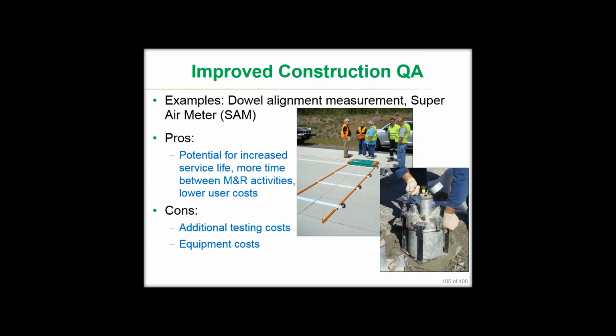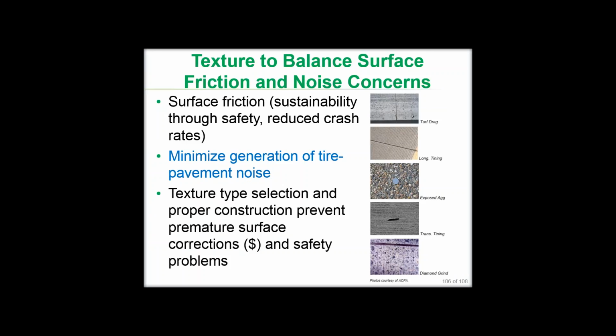We're seeing a lot of work being done with construction quality assurance now, with measuring dowel bars with non-destructive types of pieces of equipment like the MIT scan device. We're also measuring pavement thicknesses instead of doing coring. We're using non-destructive devices for that. The super air meter, which is out there now and is being implemented in many places, giving us a better idea of the quality of the concrete without having to rely just on total air content, getting a better indication of the quality of that air void system. And all those things assist then in the durability and the longevity of that concrete, which leads to hopefully better